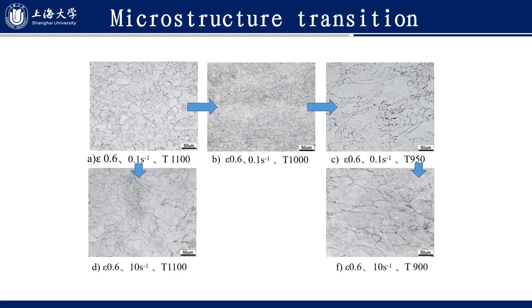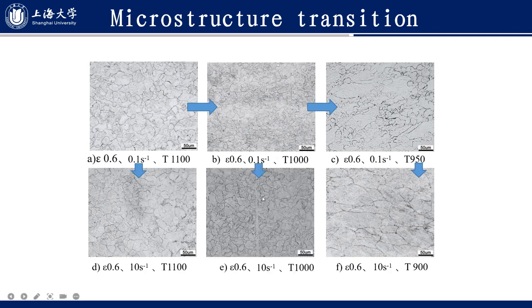These figures show the difference between the microstructures with different strain rates. It is clear that at 1000 degrees C, the deformation makes the steel a fully recrystallized microstructure. Very fine austenite grain sizes are obtained after deformation.